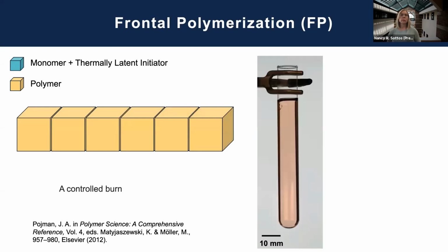Most of the work on frontal polymerization has been done in this highly advanced mold of a test tube, and you basically trigger it with a small amount of energy. I'm going to start the video after we trigger this with a soldering iron for demonstration purposes. The soldering iron is already gone. And you can see the front start to move. This is also changing color as the monomer polymerizes. So as it goes from monomer to polymer, it's going from a pink to a yellow-orange color. And you see it just fully and smoothly propagates down until you have a full conversion of the monomer.